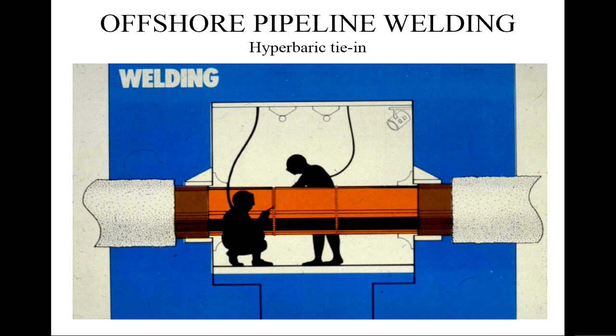So hyperbaric welding, using that sort of system, a couple of welders working with the normal welding processes that you see, but they're working at high pressure, so they don't have a great deal of time when they can produce good quality welds. You've got good sealing on the outside here. You'll notice that the concrete that's usually around the outside of this pipe that enables it to sink has been removed by this process. So that's something else that you've got to think about doing. It adds to the cost of these subsea welds. So you really don't want to do welding underwater if you can get away with it. For a tie-in like this you have to, but you'd rather avoid that.